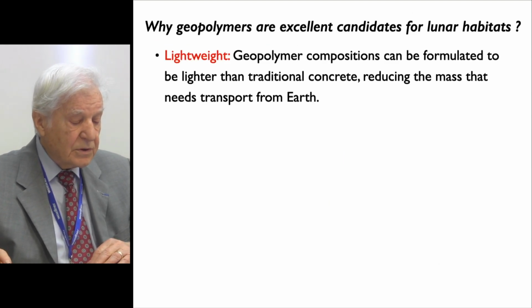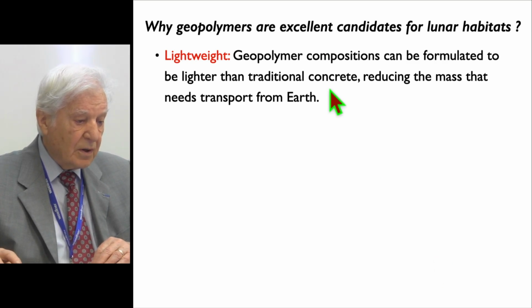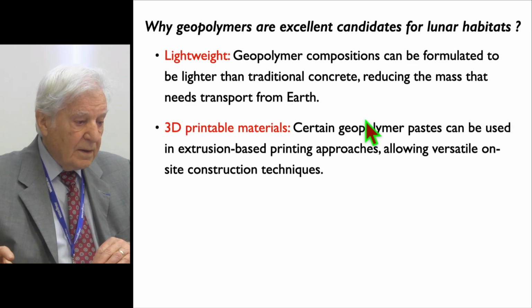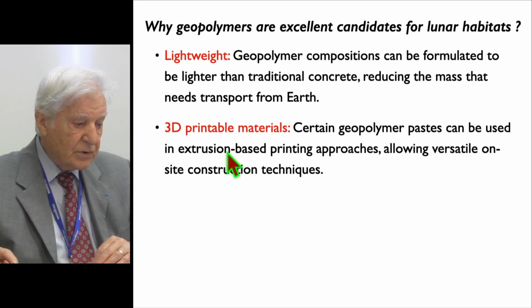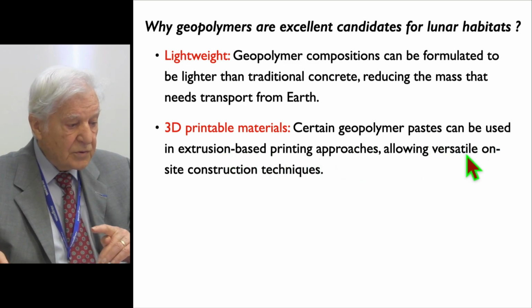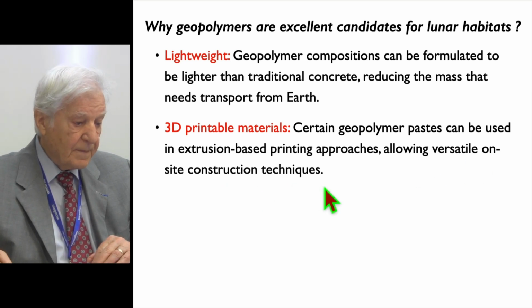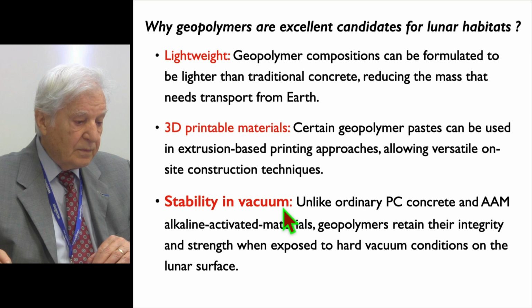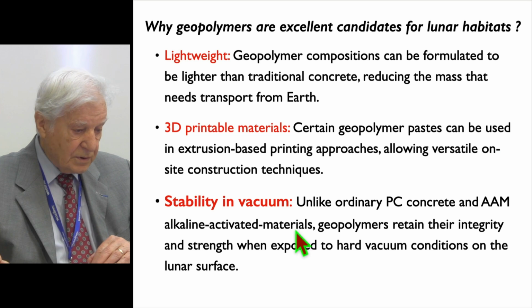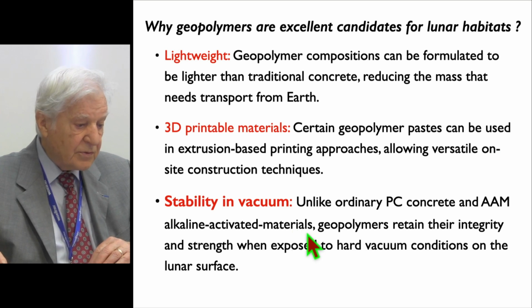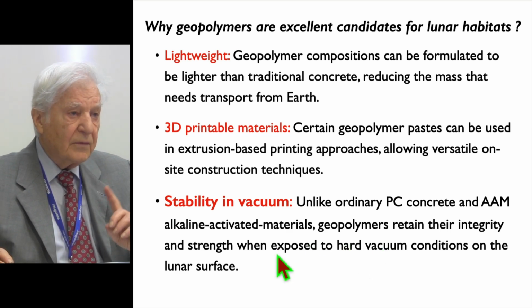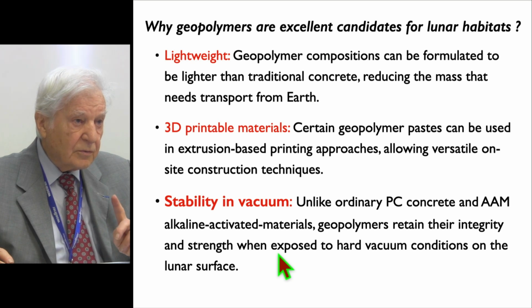Lightweight. Geopolymer compositions can be formulated to be lighter than traditional concrete, reducing the mass that needs to be transported from Earth. 3D printable materials. This we know. Certain geopolymer pastes can be used in extrusion-based printing approaches, allowing versatile on-site construction techniques. Stability in vacuum. Unlike ordinary Portland cement concrete and alkali-activated materials, geopolymers retain their integrity and strength when exposed to the hard vacuum conditions on the lunar surface. And if you remember, this is due to the structure, the quaternary structure.